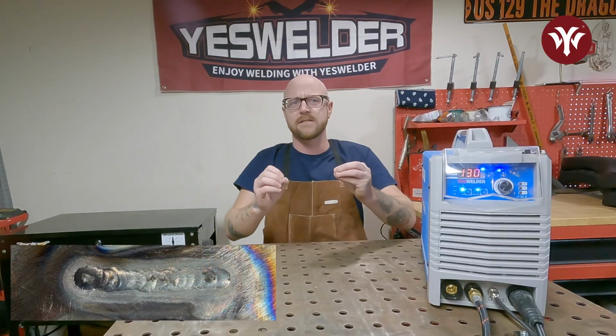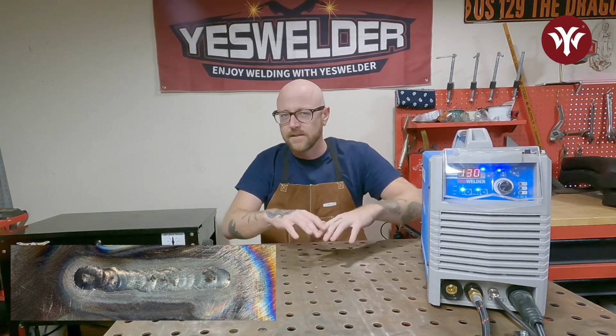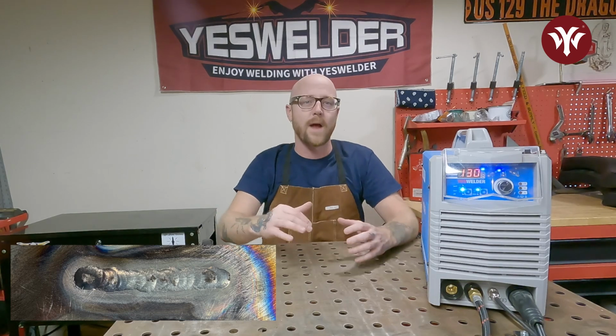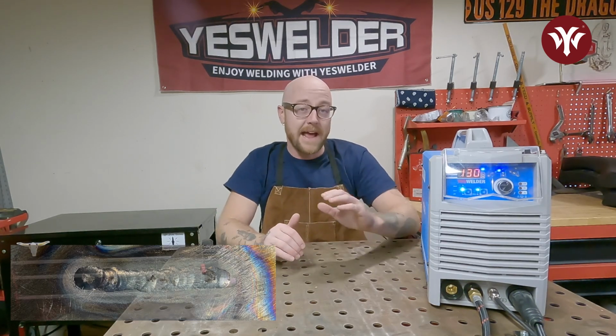So we went down to 130 amps, which is just a bit over 5 amps over that 1 amp per thousandth. And as you can see with the weld we just did, it's still a little hot. It's a little bit smoky in appearance. It's a little erratic.